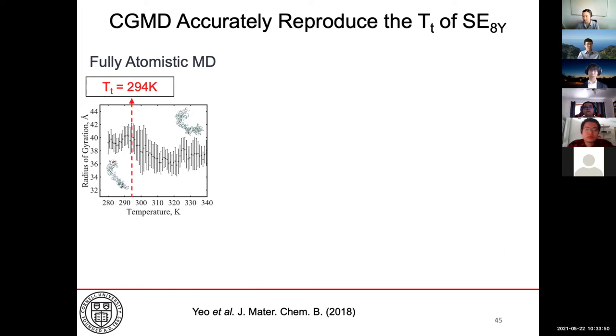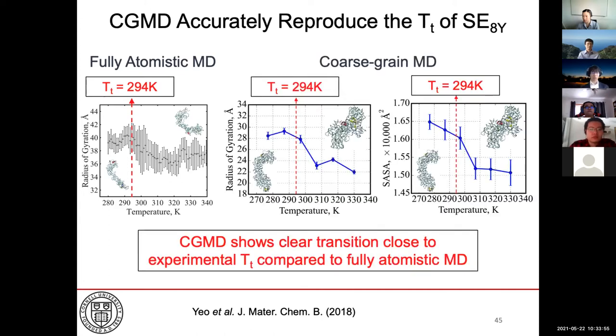Now, by folding the protein with fully atomistic molecular dynamic simulations, the transition appears to be captured as well, but this transition is very small with quite a lot of noise in the data. Now, in contrast, my coarse-grain results show a very distinct transition that's close to the experimental transition temperature for both the radius of gyration and the solvent accessible surface area. And observation of the molecular structure over here also shows a collapsed structure from a somewhat more elongated conformation at low temperature. And the amount of noise in the data was also significantly reduced. And thus, we show that this coarse-grain model achieved both a speed up in sampling as well as improved accuracy.